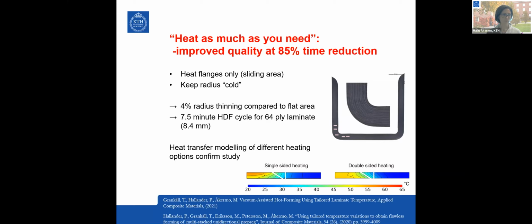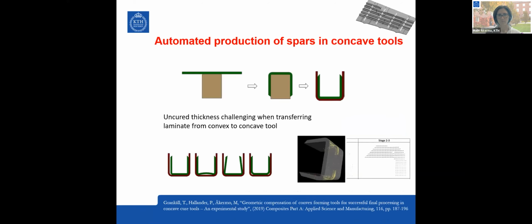The second step, considering this having a good control over geometry, considers producing these spars. If you have a lot of spars that you want to join here, they can't have an outer surface that is rough. And if you cure them on a male tool, a convex tool like this, it will have a bagging side here which is rough, and you will have pore fitting in between. It's preferable to cure it inside a female tool, having the outer surface shining and flat, and thereby be able to put them together.